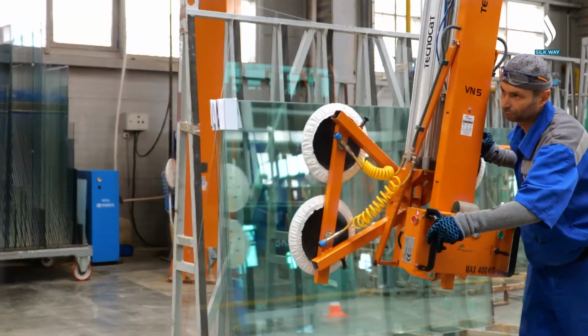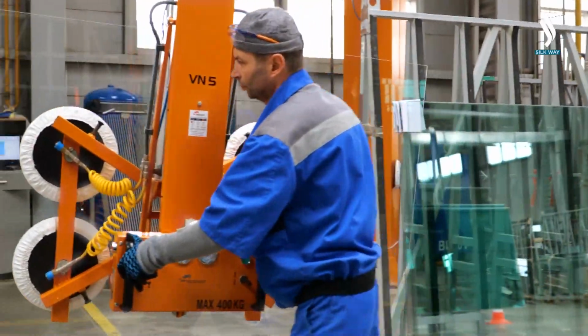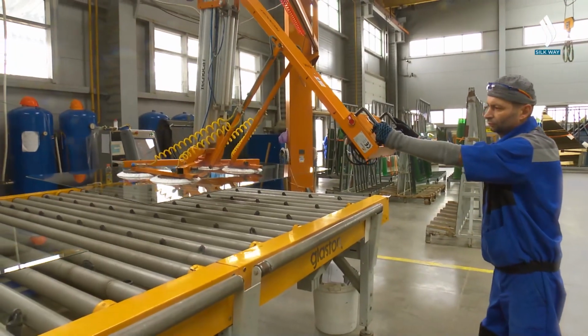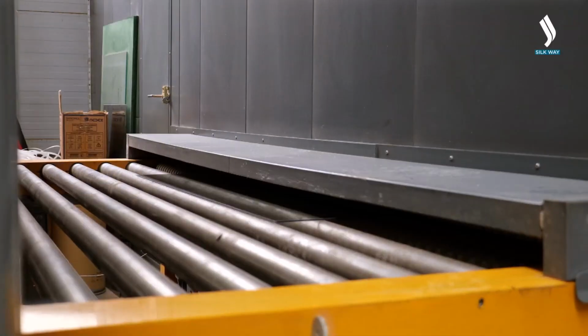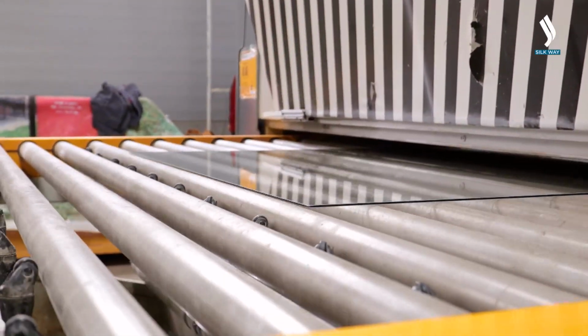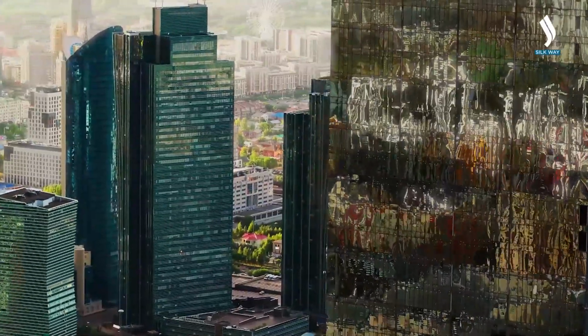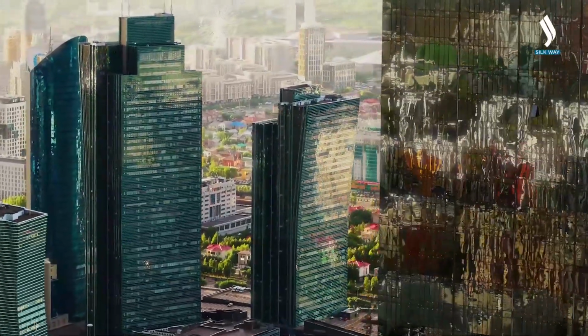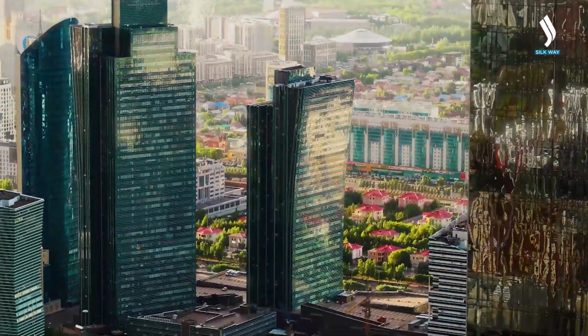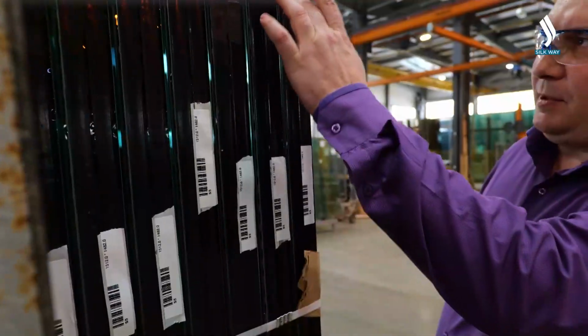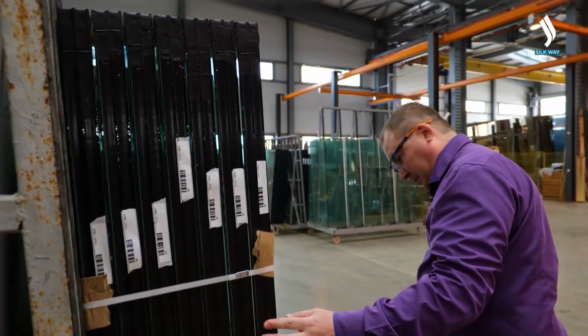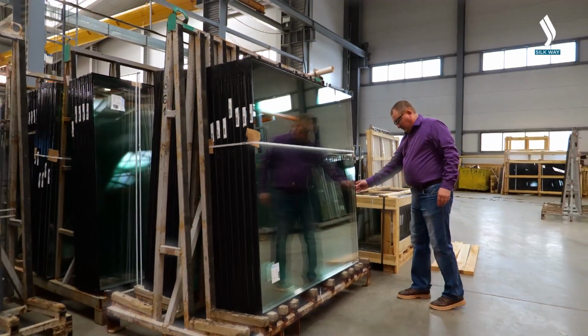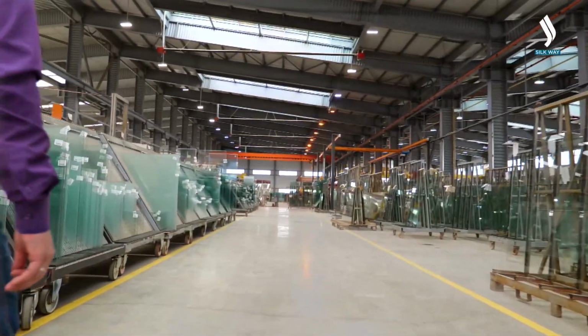Heat-reflecting glass is used to protect the premises from sunlight and heat rays. Thin layers of metals and their oxides are applied to the surface of the glass. The glass's light transmission is 30 to 70%, while heat transmission is 40 to 60%. Due to the fact that in such glasses most of the infrared rays are not absorbed but reflected, the glass itself is barely heated. Due to the reduced radiation from the room, they increase heat protection in winter. Glass can have different colors such as golden, blue, orange, etc. Remarkably, Kazakh enterprises produce several types of glass, which is used both in our country and abroad.